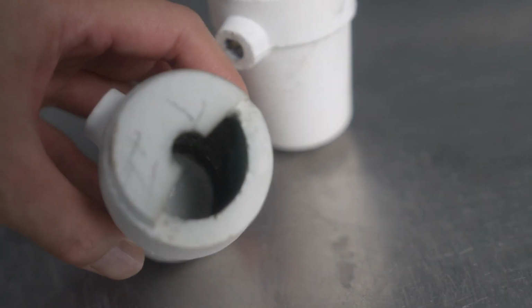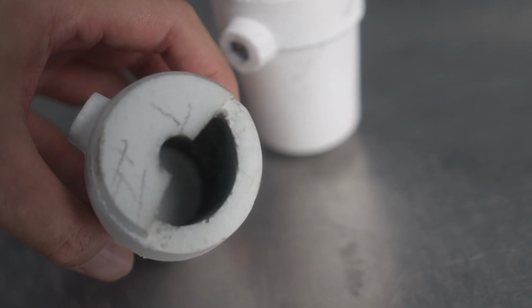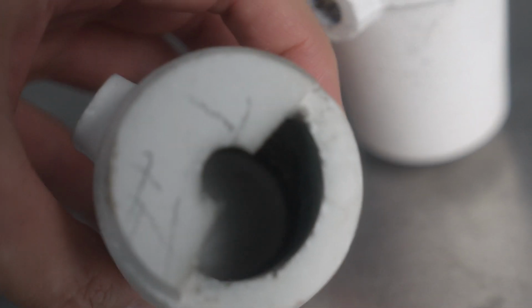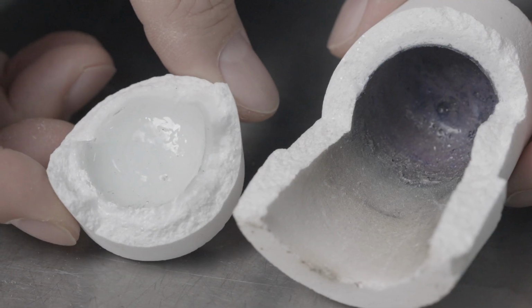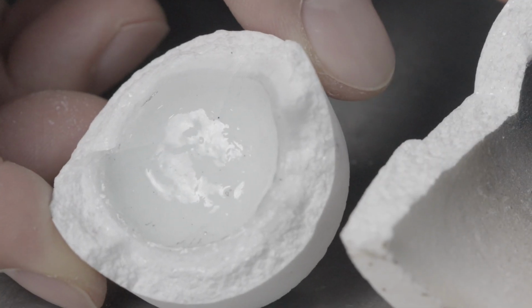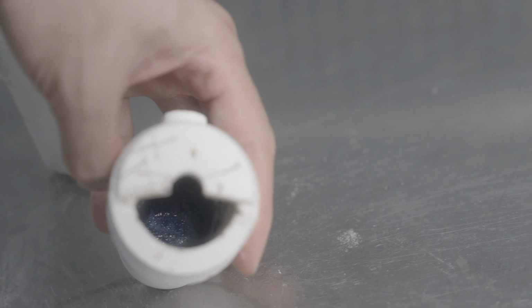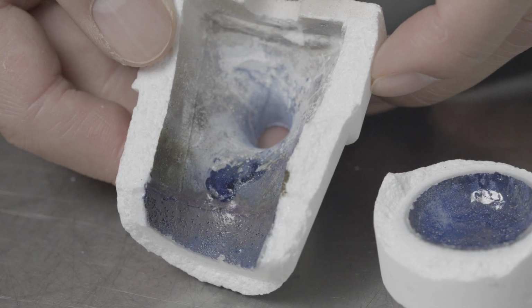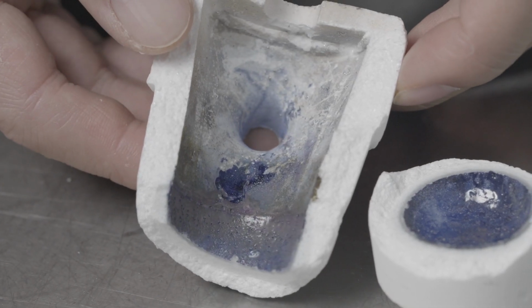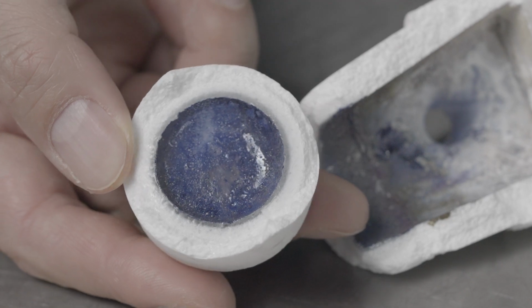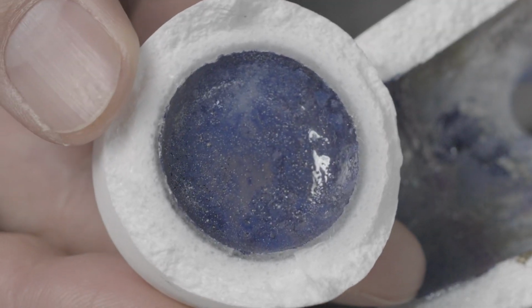We quite often see this glassy, reflective surface on the inside of the crucible in our casting equipment. Sometimes it's translucent, sometimes white, sometimes even bluish in tone. This is very common, and we most often see this with crucibles that have been reused numerous times.